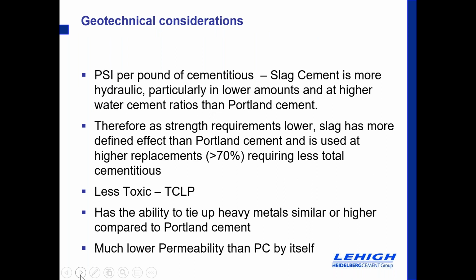PSI per pound of cementitious. Slag cement is more hydraulic in lower amounts and higher water-cement ratios than Portland cement. That's a relatively easy sentence, but I always like to give a little color to it. One of my first geotechnical applications was slag cement in mining backfill, where we were replacing Portland cement with slag cement to achieve low strength fill in these vast chambers underground.